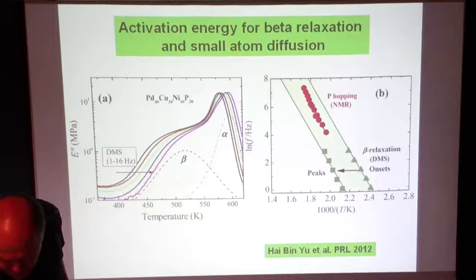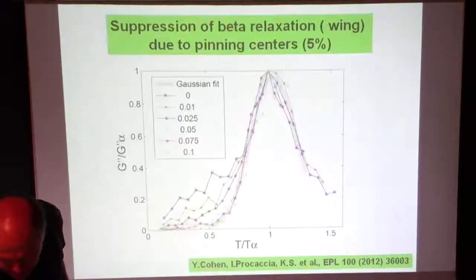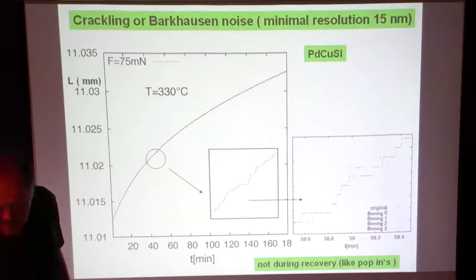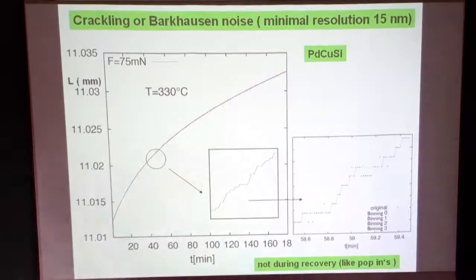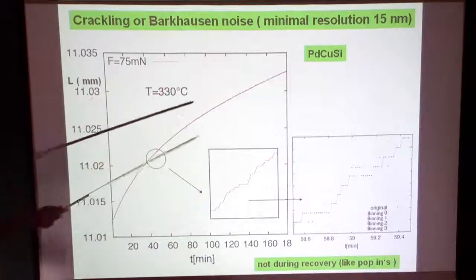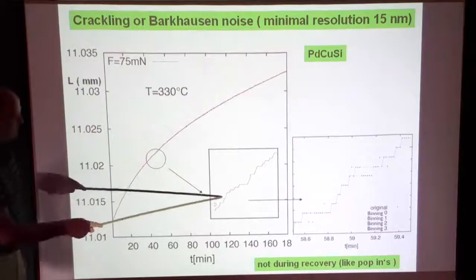Okay, I showed you that. I skip this pinning part and come to the avalanches. So now we're doing this. We did these creep measurements all the time because we want to see how it looks in the volume activation. And during this measurement, we saw this is just the length versus time for a certain sample again. We saw that they have some jumps in the system.